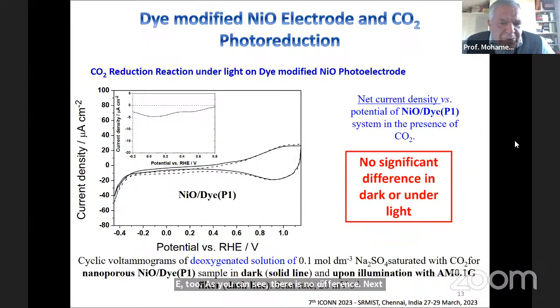So when you take the nickel electrode modified by the dye, where you absorb the dye, there is also not a significant difference between both states, with or without light, under dark and under light. So there is a very, very little difference.